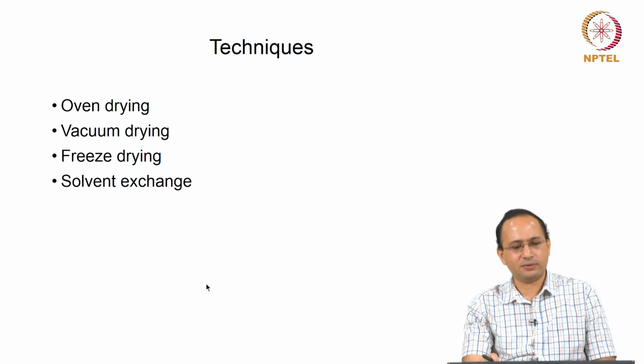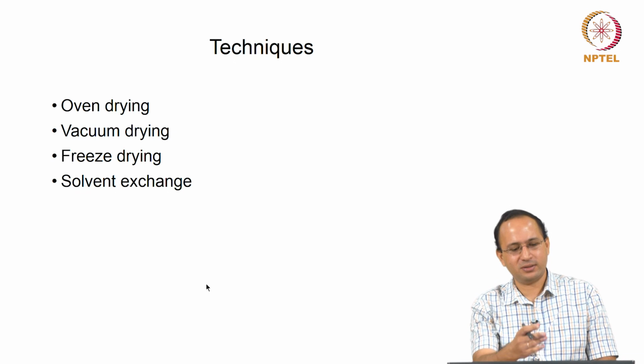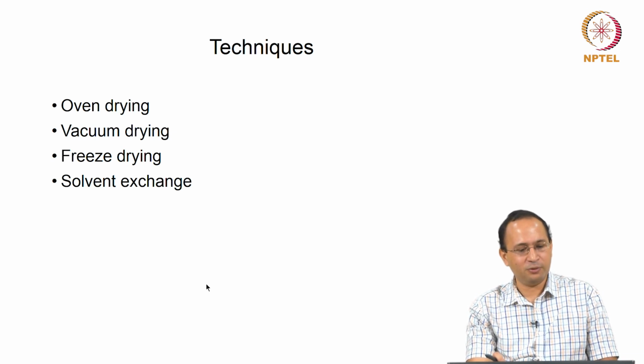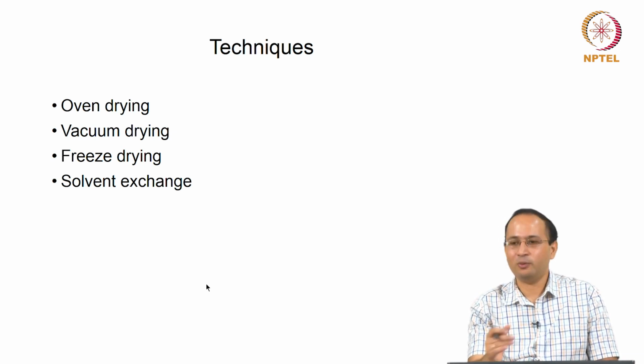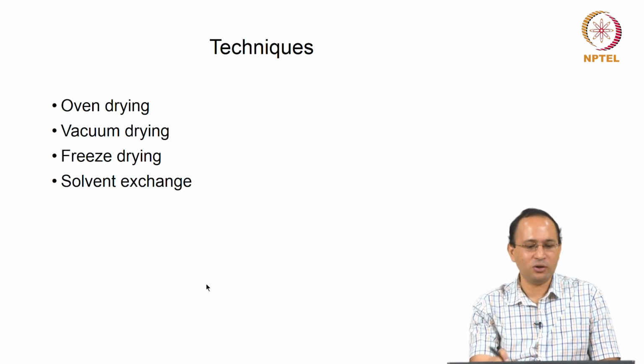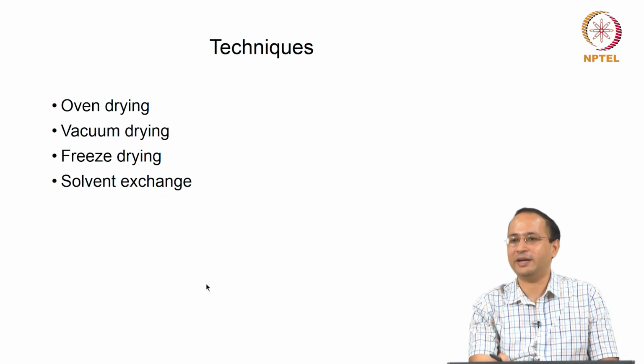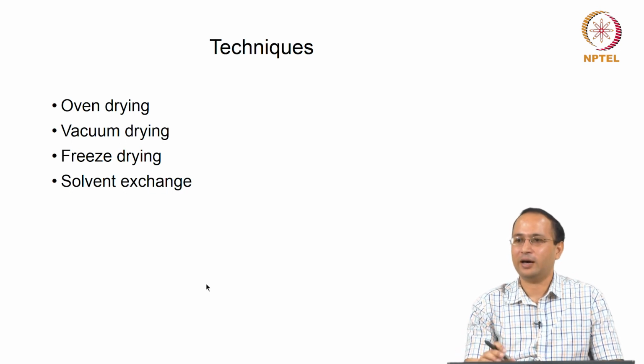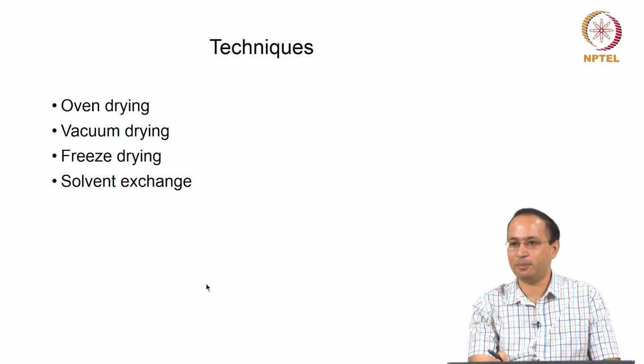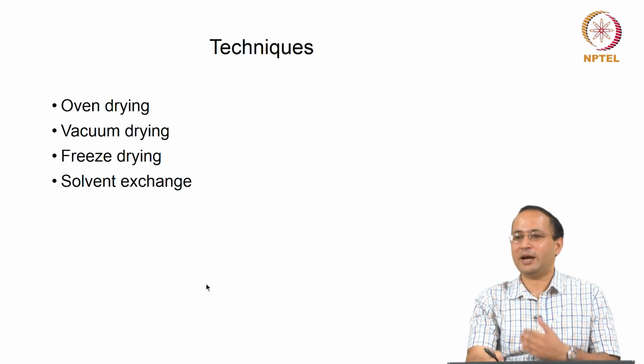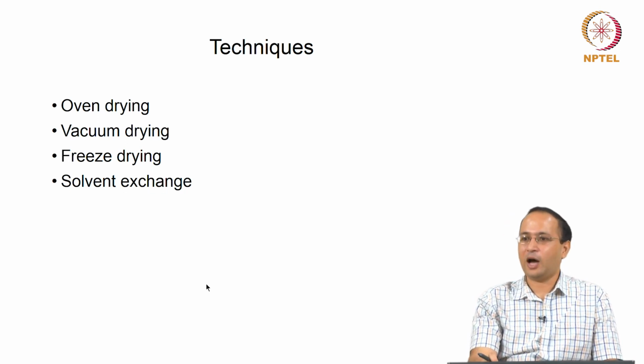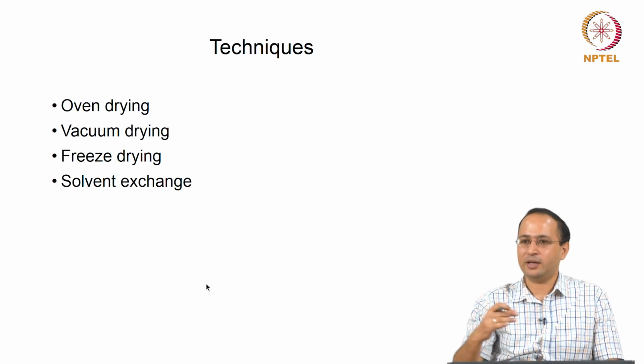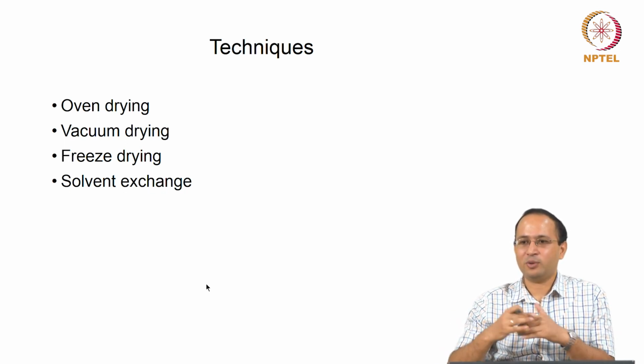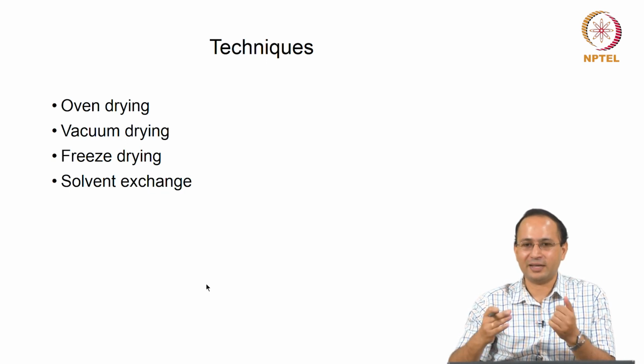So there are different techniques for hydration stoppage that people have used, but there are always some advantages and disadvantages. So you see oven drying, vacuum drying, freeze drying, solvent exchange. What do you mean by oven drying? You are putting your sample at a really high temperature to remove the water. The idea is to remove the capillary water, right. How do you stop hydration? You mix cement and water, you have formation of hydration products like calcium hydroxide, calcium silicate hydrate, Ettringite, right. Also you have some capillary water left. So you have to remove the capillary water.